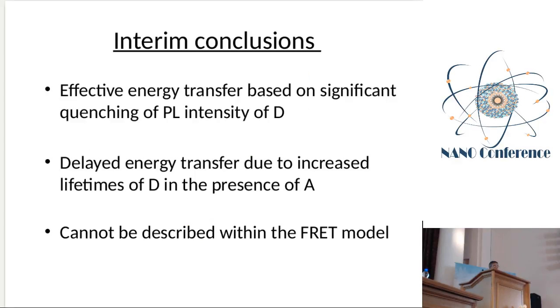So we have interim conclusions: we have effective energy transfer based on the evaluation of intensity change, but we have delayed energy transfer due to the increased lifetime of donor components in the solution in the presence of the acceptor. And these results cannot be described by the FRET model.